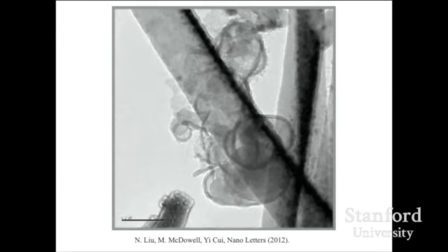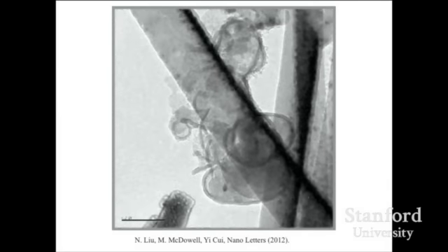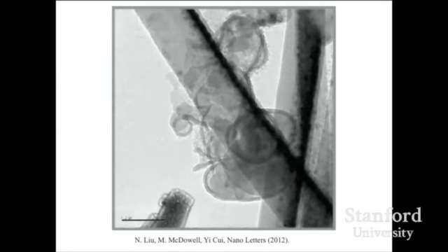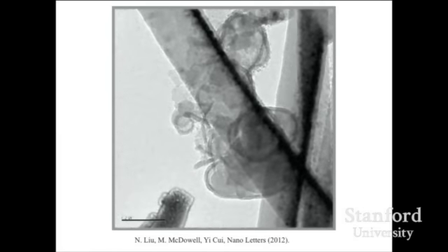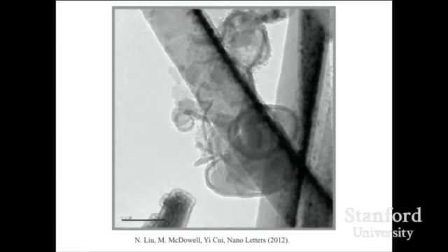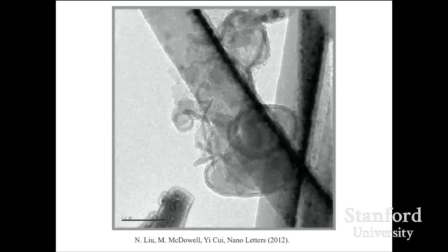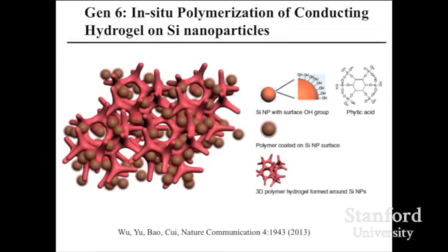If you talk to our EE professors right here, you say, I want 10 nanometer silicon oxide, I want 100, they can exactly give you that thickness. Using that type of synthesis, using silicon oxide as a sacrificial layer, you can engineer this empty space and allow the volume expansion to just exactly fit. So using the yolk shell structure, we actually can cycle many, many times.